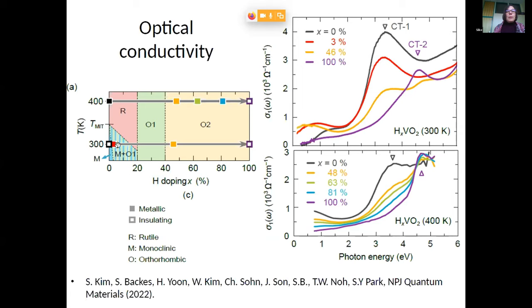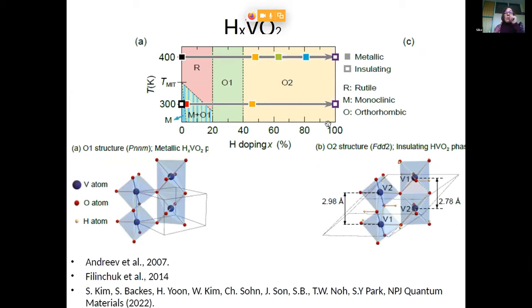You continue. So we are going here. And then at 100%, you actually reopen up the gap. If I start here, that is the high temperature measurements down here, you start from the metallic compound, you make it worse metallic, and eventually you're in the insulating phase. Okay, on the way, you are actually crossing what is labeled as orthorhombic 1 and orthorhombic 2 phase. So the structures are given here.